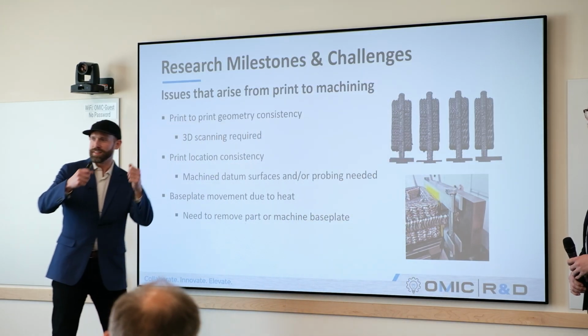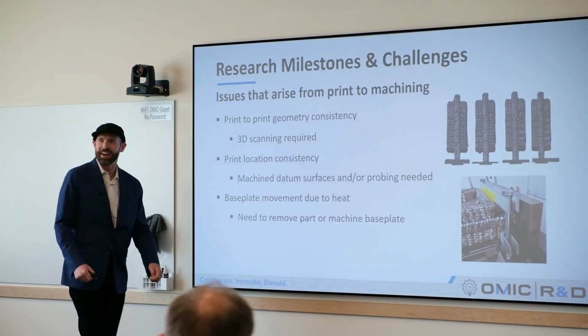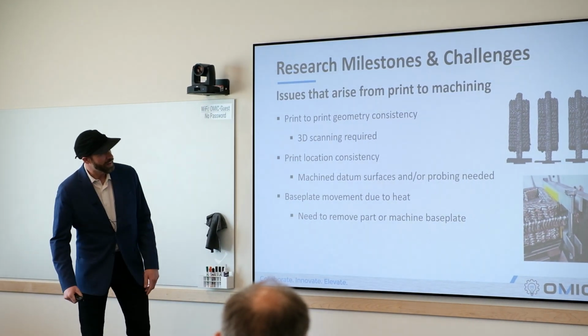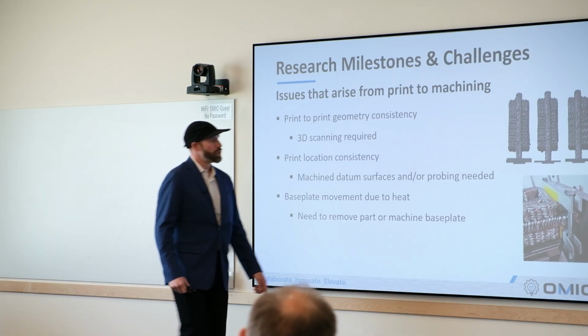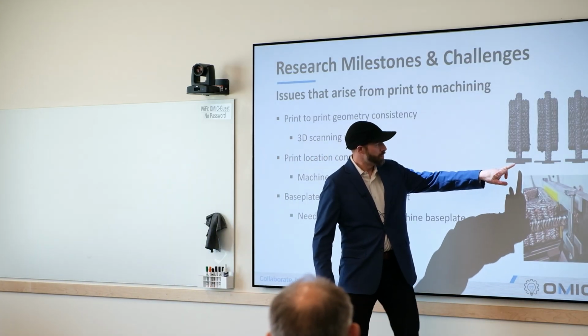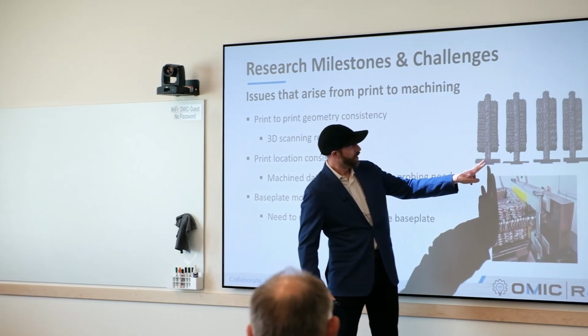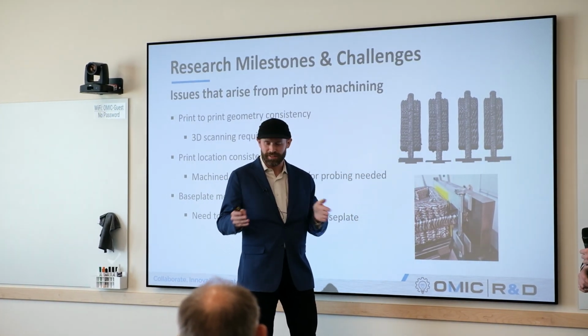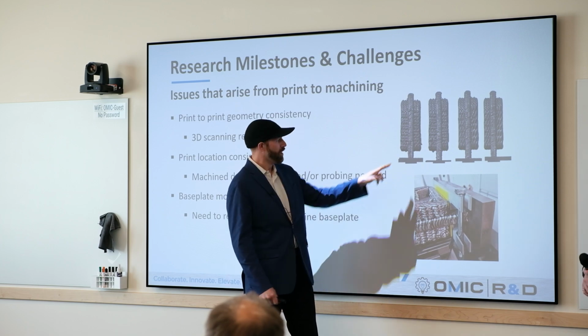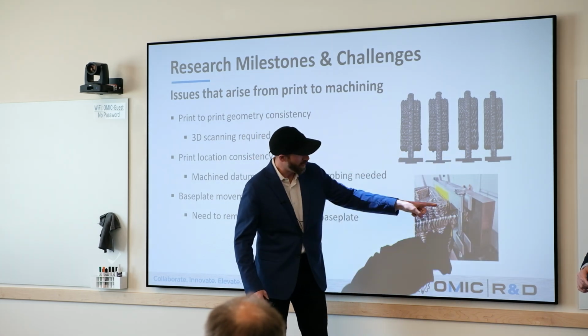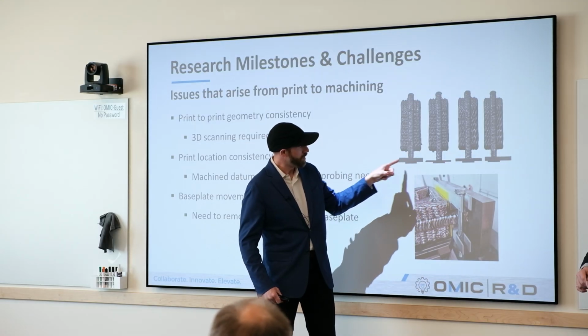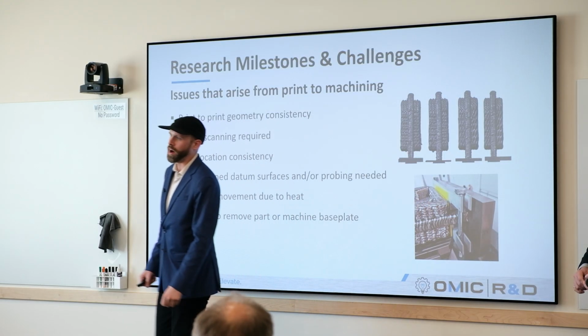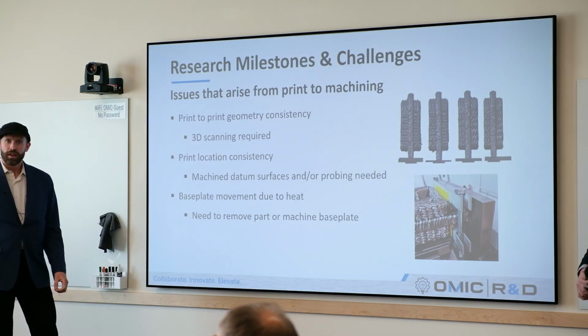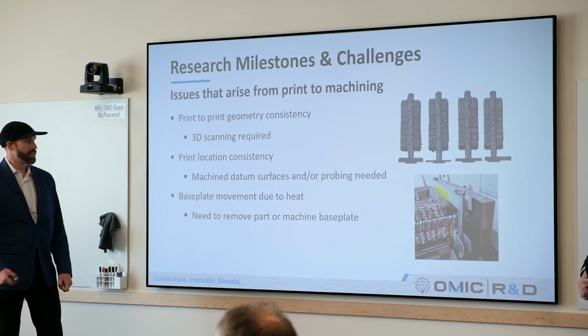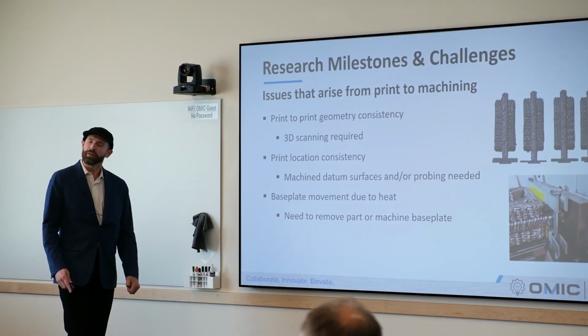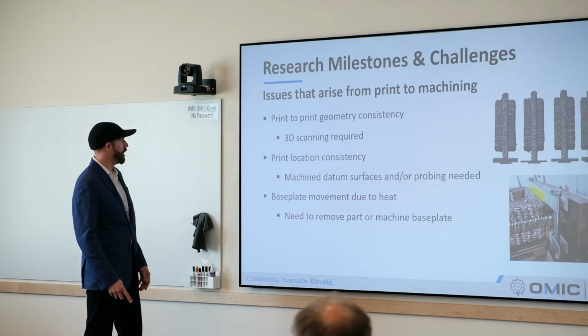So slamming that into a CNC machine and just probing it and hitting go is kind of out of the question, unless you have a nicely scanned part like we have here, and are able to machine in some datum surfaces as correlated to our printed datum surface, the most uniform piece we have from the print, which is this web down here. And that's how we held the plates to actually put these locating surfaces for a dovetail fixture on the bottom. So you have a flat surface, we're able to grip extremely strong and take some very heavy titanium cuts to the profile of this to more net.